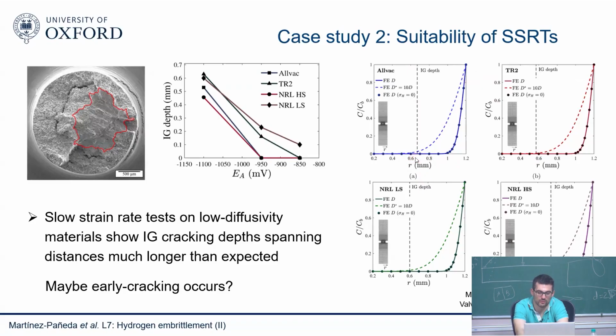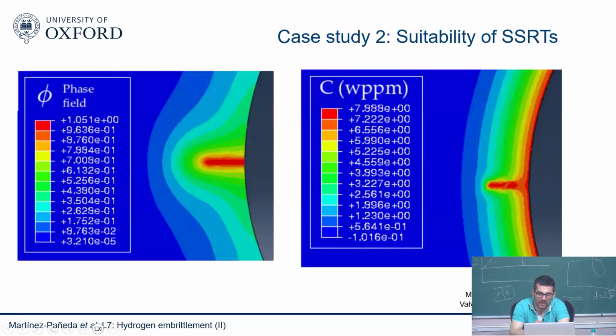So we tried to figure out if we can learn that from the model. And then one aspect that is critical in that case, and this is a slide I just added last minute because I thought it would be useful, is that your phase field model needs to capture how, as the phase field grows, as the crack grows, the hydrogen concentration follows. And it won't follow if you pre-charge your sample and are running a test in an inert environment. But if you're running a test in a hydrogen-containing environment, the hydrogen must, of course, follow.